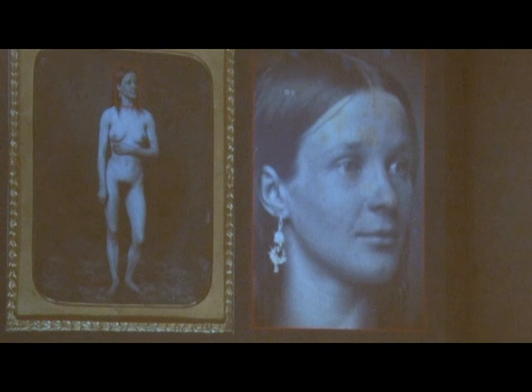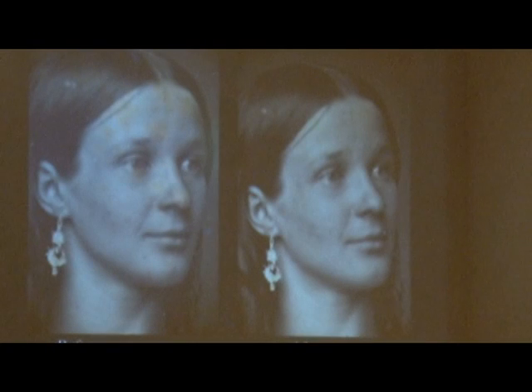This plate had a record that it was cleaned with thiourea in 1996. 17 years later, it developed these brown spots. These spots are also called Daguerrean measles because that's what they kind of look like. And it's kind of seen in the overall of the normal light image, but this is when the negative viewing mode is helpful to see those tarnish. This is before and after treatment. And a close-up.